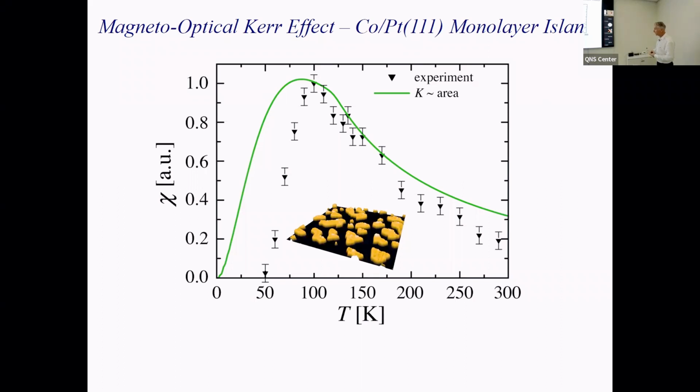So this is the zero field susceptibility as a function of temperature, and it characterizes what is called a superparamagnetic system. This means that at low temperatures, these islands are ferromagnetically ordered. And when you go to high temperatures, for example, at this temperature, which is referred to as the blocking temperature, they still stay ferromagnetically ordered, but the whole spin of one island can reverse.